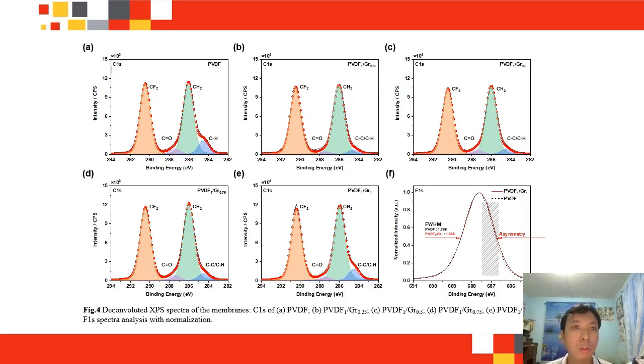Peaks at 290.5 eV and 286 eV were assigned to the CF2 and CH2 groups in PVDF, respectively, while additional peaks at 287.4 eV and 284.8 eV were attributed to CH bonds and carbon atoms bonded with electron withdrawing groups, such as CO, amides, and esters. So these features likely originated from fillers used during the commercial synthesis of the PVDF.